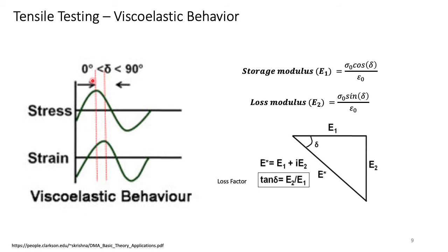So if this angle is 0, that means the material is 100% elastic. That means cosine 0 is equal to 1, so the storage modulus is at a maximum. That means it's 100% elastic. If the phase angle is equal to 90, cosine 90 is 0, which means that the storage modulus is at its minimum, which is 0. That means the material is 100% viscous.